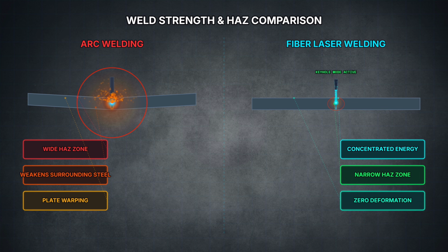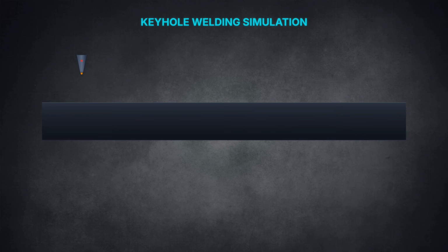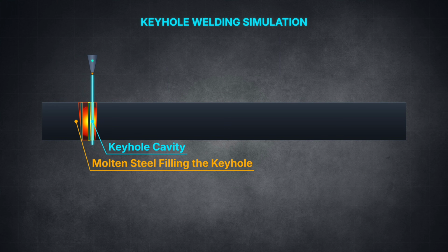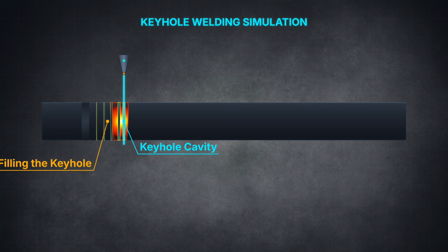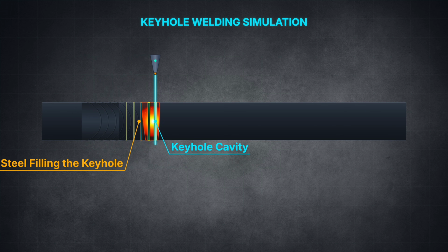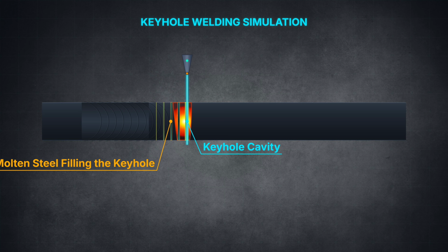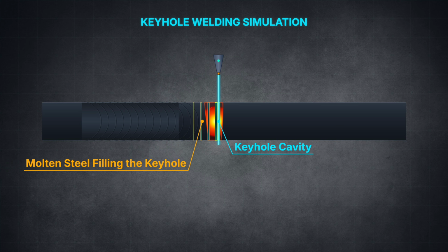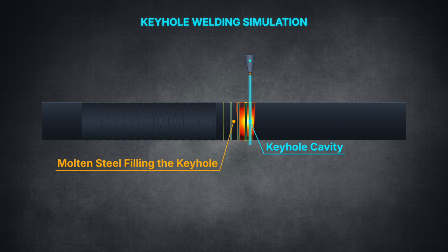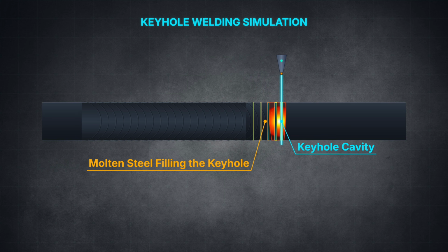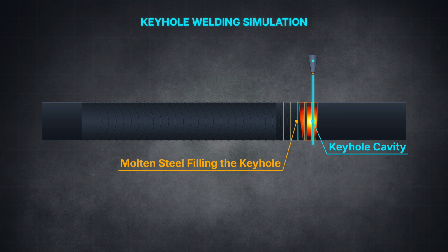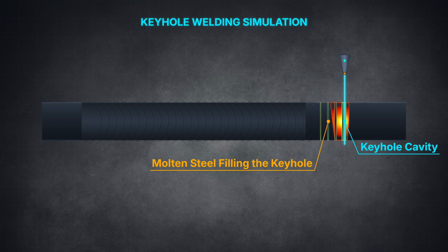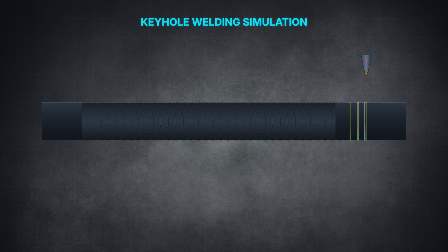To achieve this, the robot utilizes a mechanism called Keyhole mode. In Keyhole mode, the laser heats the steel at an extreme energy density. Instead of melting the surface, the 6 kilowatt laser vaporizes a tunnel straight through the 4mm plate. The pressure of the vaporized metal keeps this tunnel open. As the robot moves forward at 3 meters per minute, the liquid metal flows around the sides of the tunnel and solidifies instantly behind it.